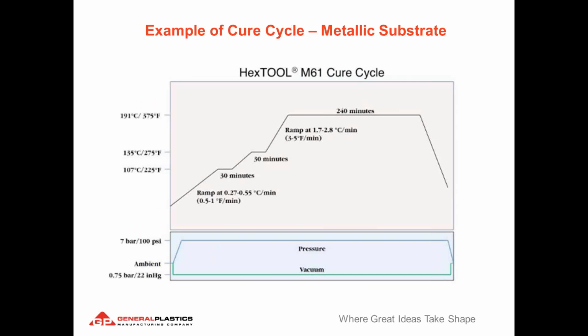So getting back to curing profiles and temperature considerations, from the HexTool M61 user guide from Hexcel, this is the recommended cure profile. And this is based off of a metallic substrate or a foam substrate if you don't wish to use a foam again. But as you can see, you have a gradual ramp up and a hold where it equilibrates, a ramp up and a hold where it equilibrates again, and then it ramps up to its final and maximum temperature to cure, and then a cool down.